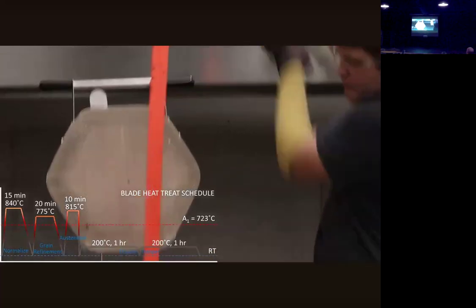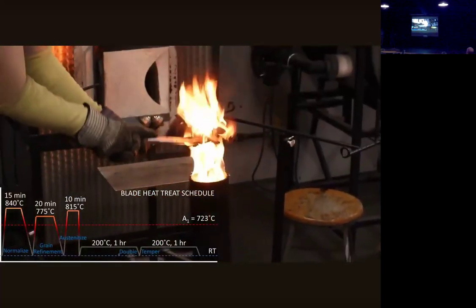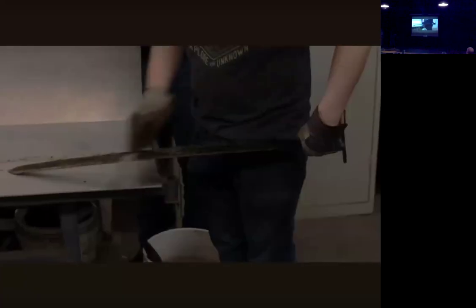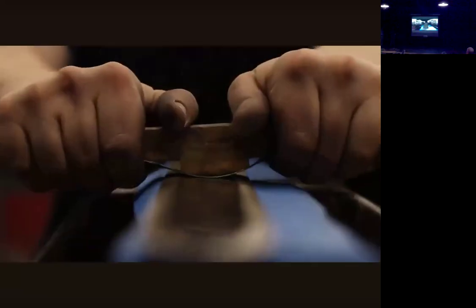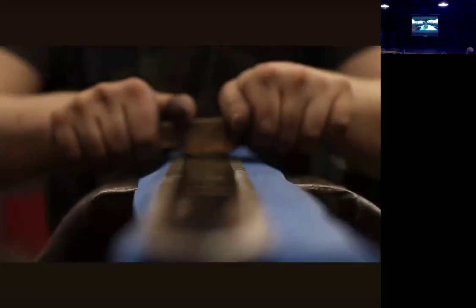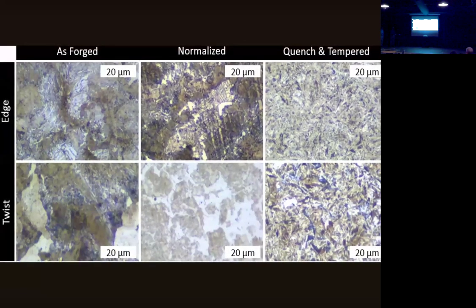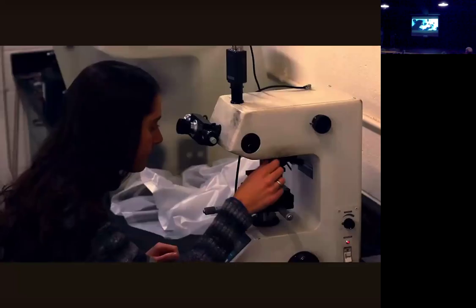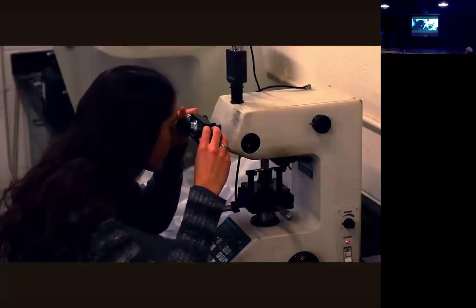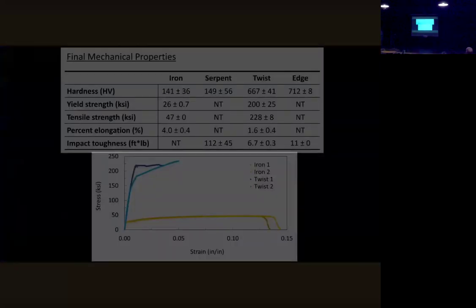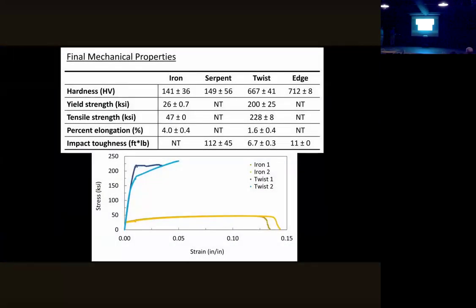After normalization, the blade was austenitized and oil quenched. A double temper completed the heat treatment. The blade was finished with hand sanding and etching in ferric chloride. Metallography, hardness, tensile, and Charpy tests were performed on material taken from the various bars. Testing on the final heat-treated material showed high hardness edge and twist material and tough serpent material.